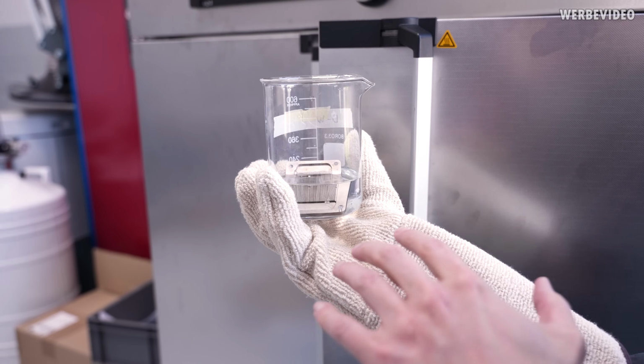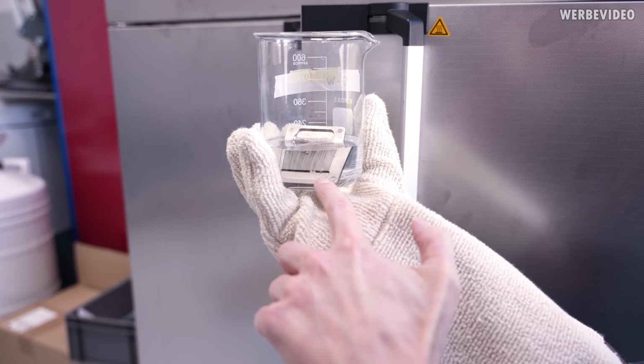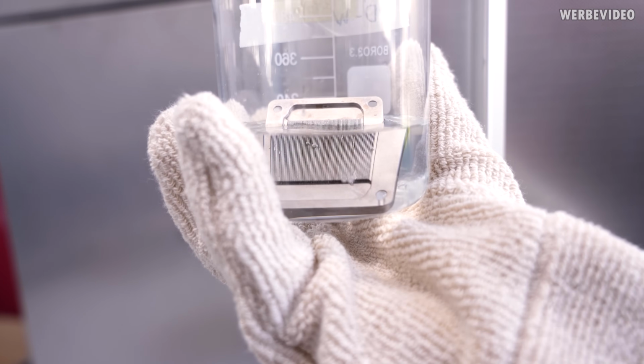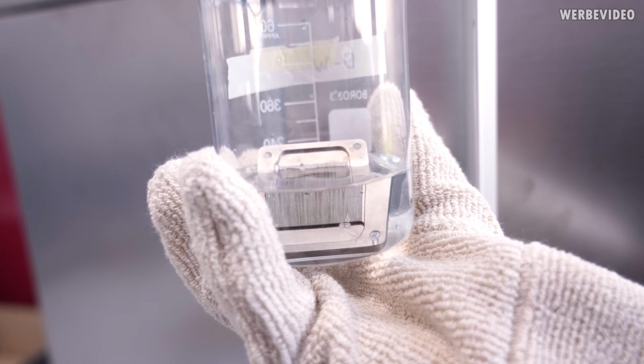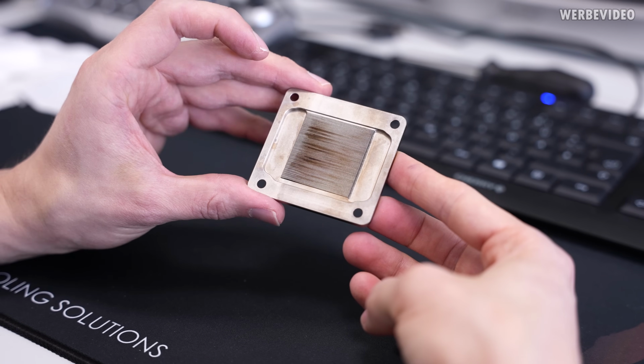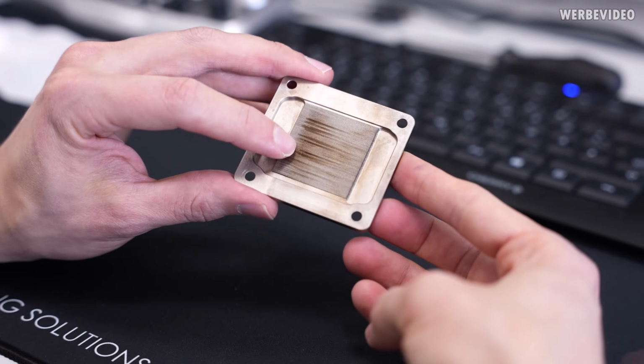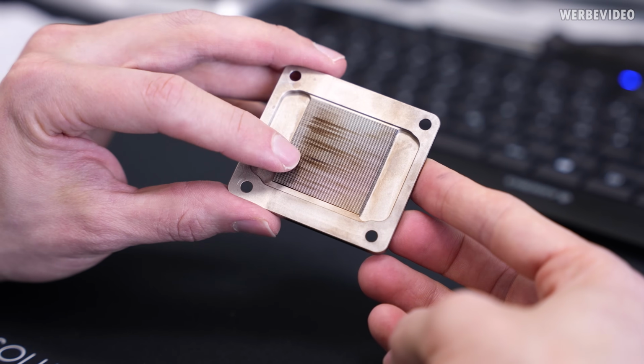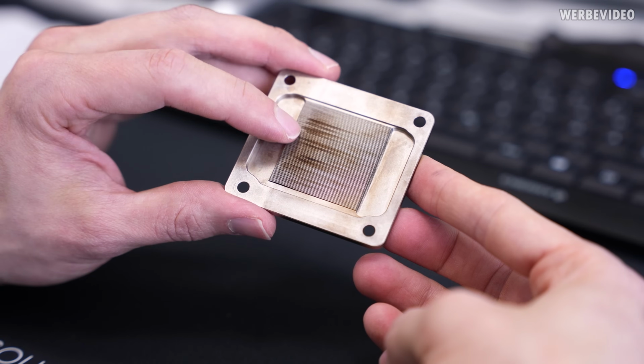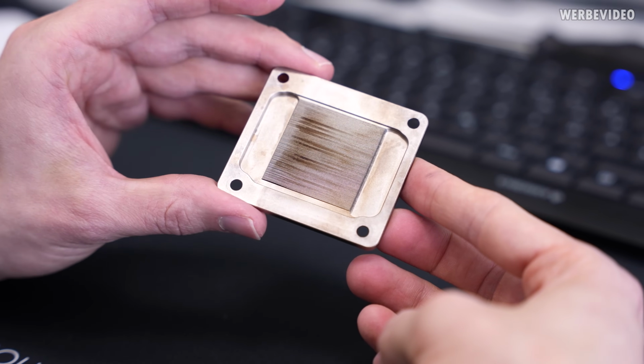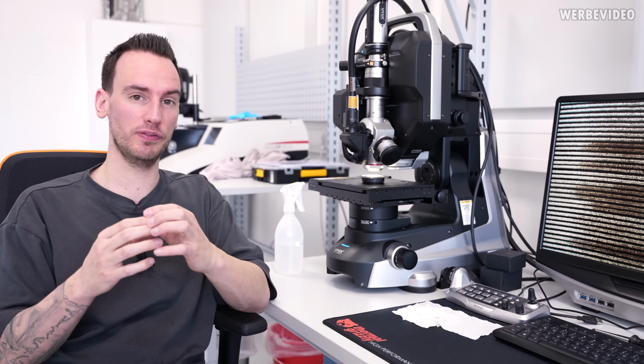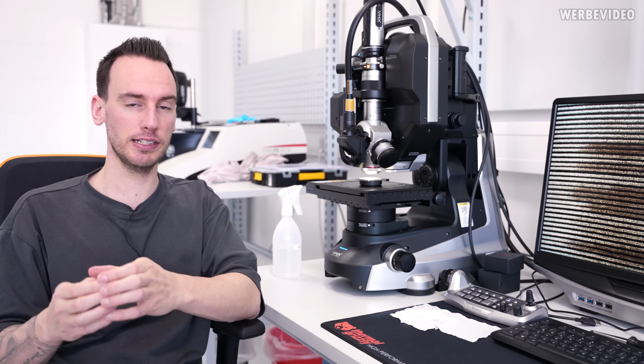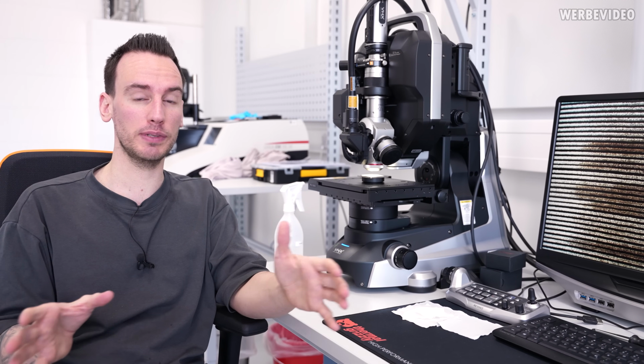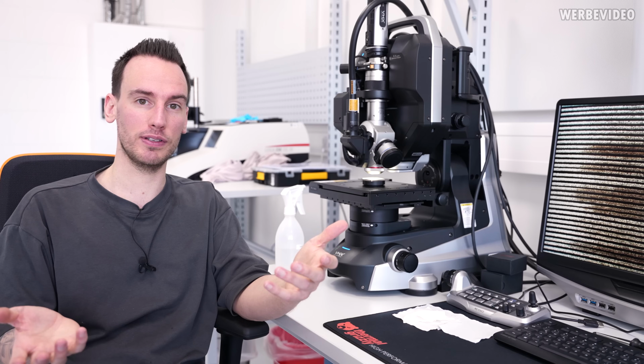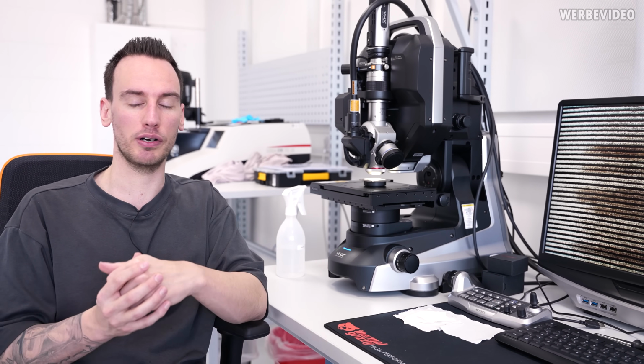And here's our part after the corrosion testing. You can already see discoloring on the fins, but we will let it cool down and take it out. Now after drying, you can see strong discoloration on top, which almost looks like the nickel plating was removed and the copper is shining through, like this brown red stuff that we can see there. And just a reminder at this point, we just put this piece of nickel plated copper inside distilled water with nothing else. There was no other material inside, and the distilled water obviously didn't contain any other weird parts of coolant or anything.